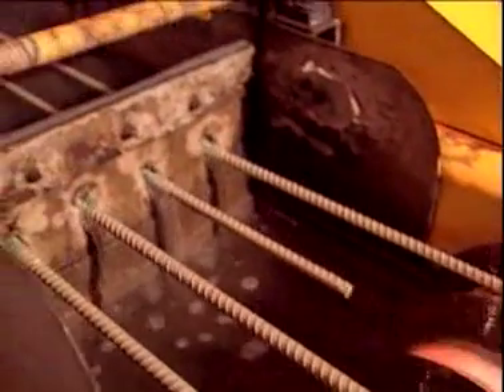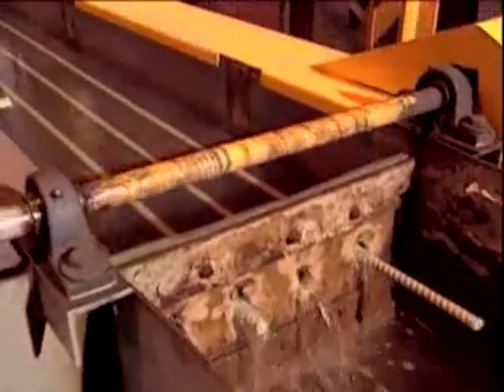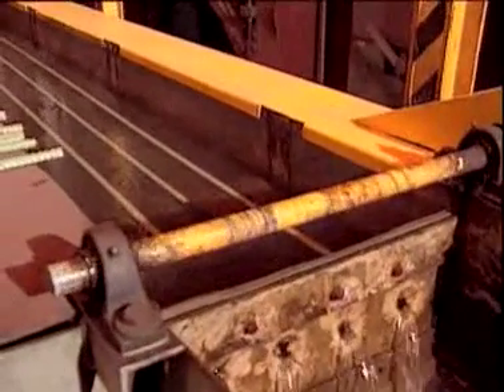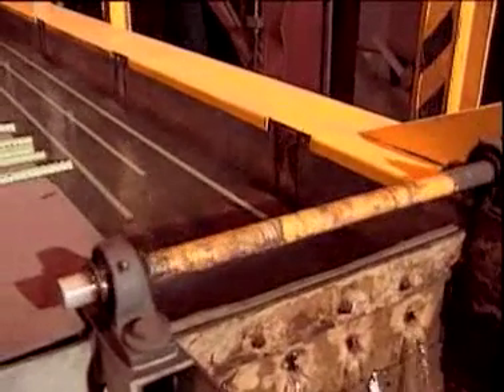Following the powder application, the coating is allowed to cool. During this period, usually 30 to 40 seconds, the coating cures to a hardened state and develops most of its beneficial properties. A water quench, shown here, or air quench, often follows the curing period to quickly cool the bars and facilitate handling.